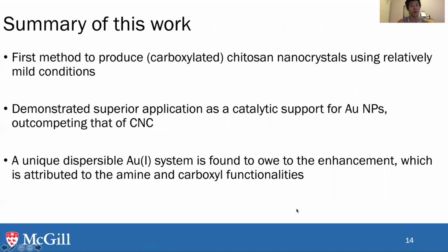And so a summary of our work includes the first method to produce carboxylated chitosan nanocrystals using relatively mild conditions, which no one has done before, as well as using this material as a superior catalyst support for gold nanoparticles, outcompeting the literature for cellulose nanocrystals, as well as a lot of other different materials out there. We attribute this to a unique dispersed gold(I) system that's owing to the chitosan amine present, as well as the carboxyl functionalities.